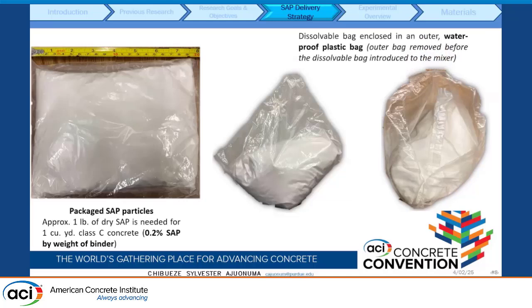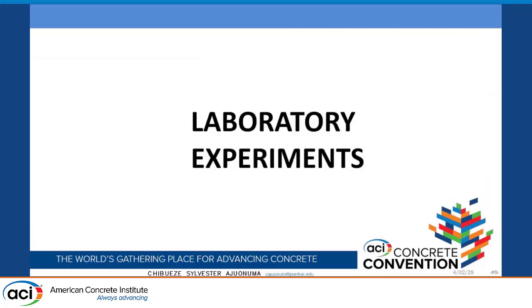And this bag, in order to protect it because it reacts with water, is enclosed in a waterproof bag, which we open, and then you toss the dissolvable bag into the mixer. Why I want to point this out is because the field trial was done in a commercial batching plant, so we needed to find an easy way to batch the SAP. And for the dissolvable bag, we did some laboratory experiments to evaluate the effectiveness of this dissolvable bag in the field.